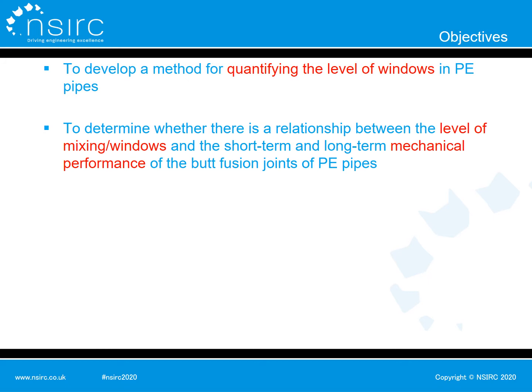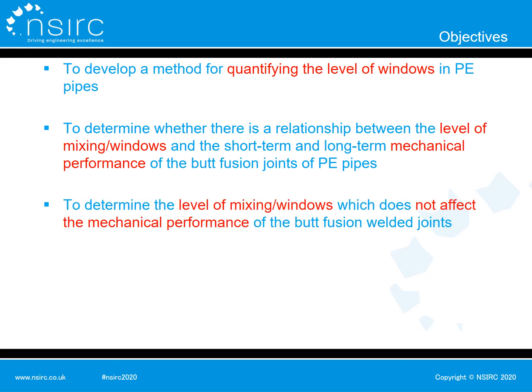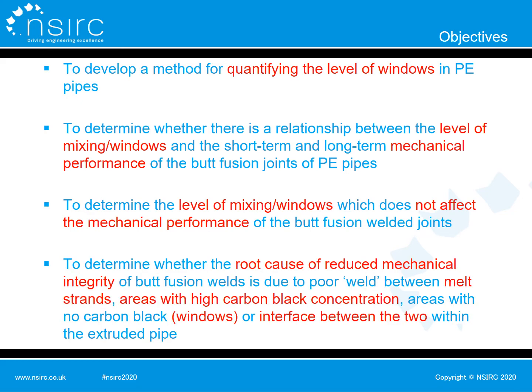If there is a correlation between the two, then determine the level of windows which does not affect the mechanical performance of butt fusion welded joints, and try to determine whether the root cause of reduced mechanical integrity of butt fusion welds is due to poor weld between melt strands, areas with high carbon black concentration, areas with windows, or the interface between the two within the extruded pipe.